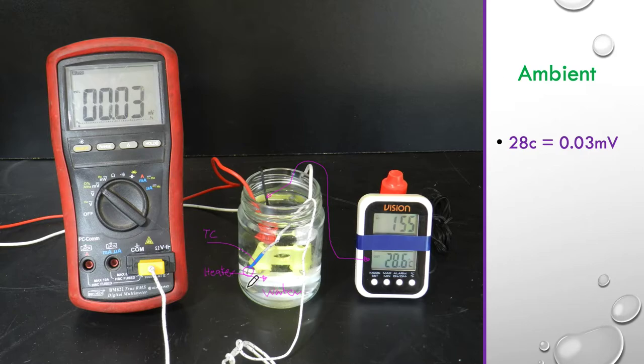Of course, the type K thermocouple, I've just got it going simply into the voltage input, and you can see on my multimeter, I'm on the millivolts DC scale here. So at ambient temperature on the day they did this, the ambient temperature was about 28 C and I'm getting about 0.03 millivolts. So it's not many millivolts. In fact, it's about 30 microvolts. So let's now increase the temperature.